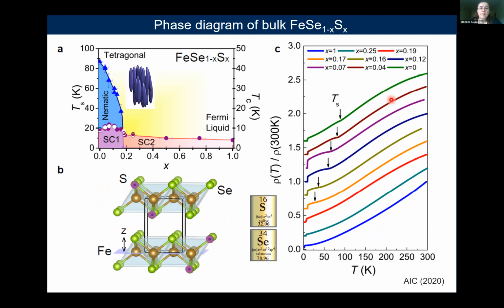So today I will discuss the phase diagram of iron selenium sulfur, and what's unique about this family is that it does not contain a magnetically ordered state. So here we have a unique opportunity to investigate the nematic electronic phase in the absence of magnetism. Magnetism is present in the form of very wide dispersing fluctuations which extend from low energy to very high energy, but there is no stabilization of magnetic order, and as such we do not expect any reconstruction of the Fermi surface.